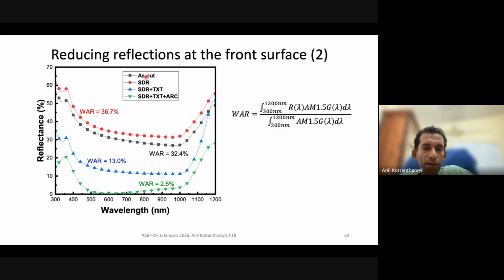You can see here the results of some of this work being done at IIT Bombay. So as cut wafers, when you make these wafers, the reflections are fairly high, more than 30%, that I already talked about. And then after texturization, it comes down to about 13%. And after deposition of the ARC layer, it comes down to about 2.5%.